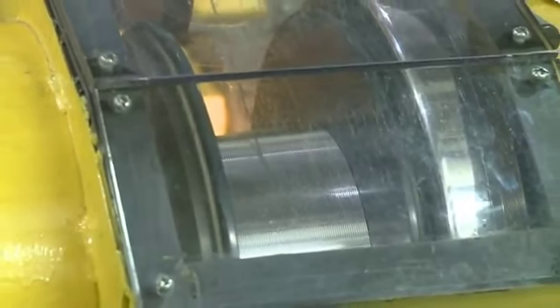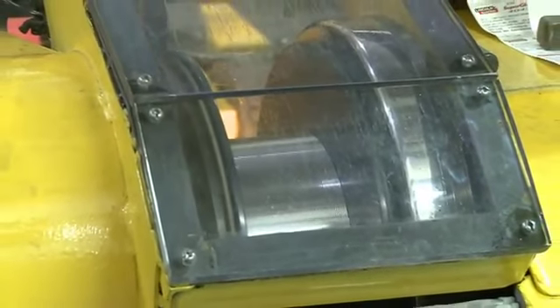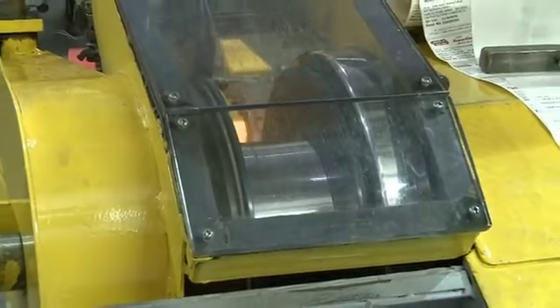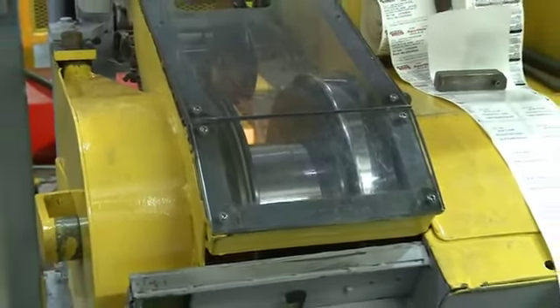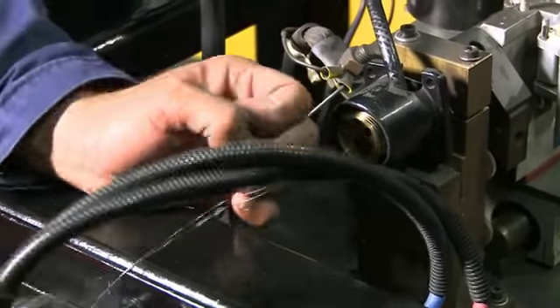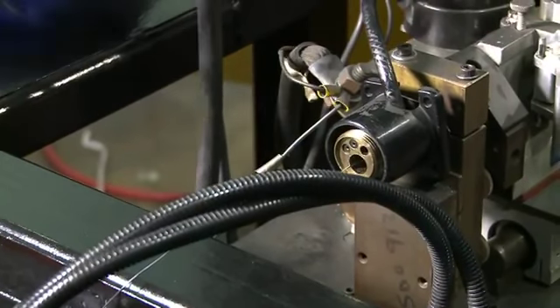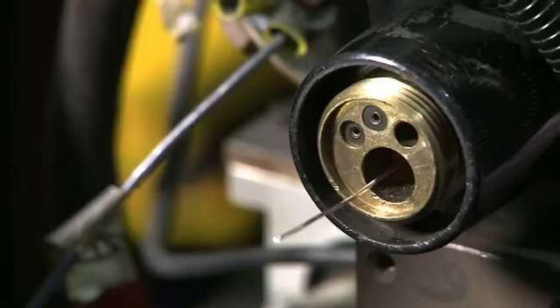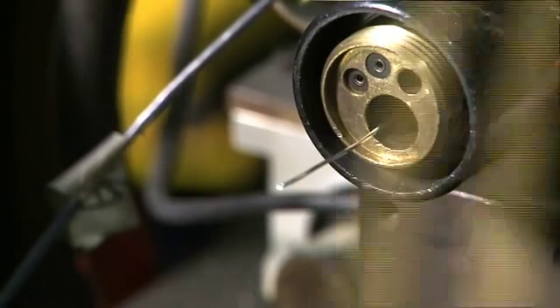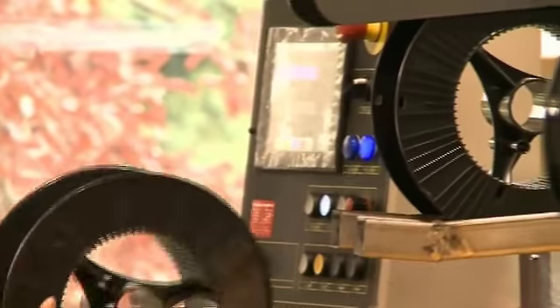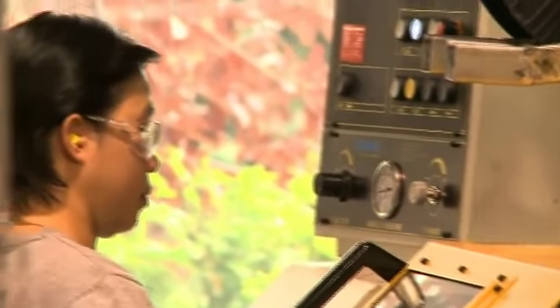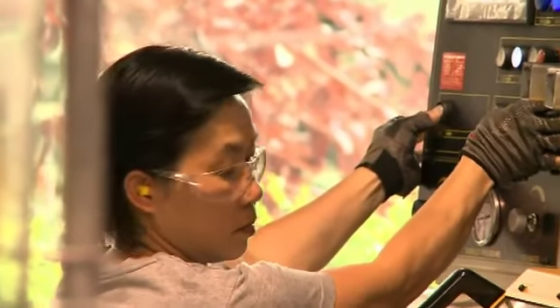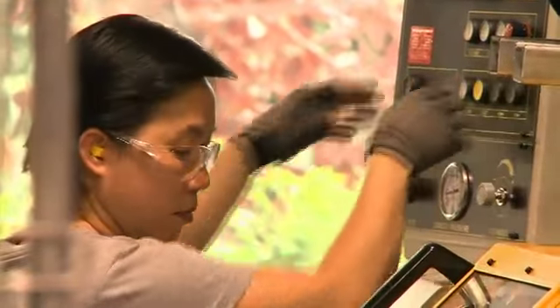Most wire manufacturers add a lubricant prior to spooling. It speeds up spooling and enhances feedability, but it can contaminate the weld puddle. We conducted a Six Sigma project to determine what was the leading cause of problems with aluminum welding wire. We determined that it was the lubricant left on the wire to make it feed and spool better. We clean and spool without lubricant. It makes spooling slower, but it results in our customer getting wire that's absolutely clean.